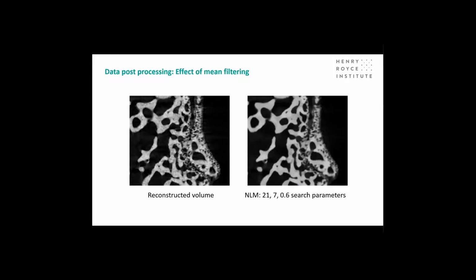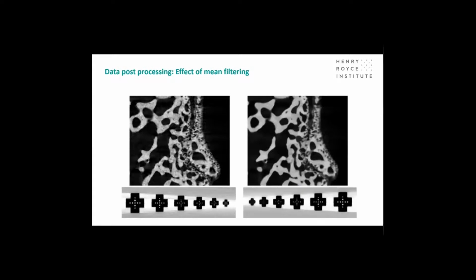Here this is actually a bone sample, but again, you can see lots of pores in this piece of bone, and you can see that when you use mean filters to improve the image quality, you can also lose information about the smallest pores. And you can see that again when you apply that mean filter to the calibration sample. On the left with no mean filtering, you can see the finest defects, whereas on the right, whilst we get better definition of larger defects, we're losing the smaller defects.